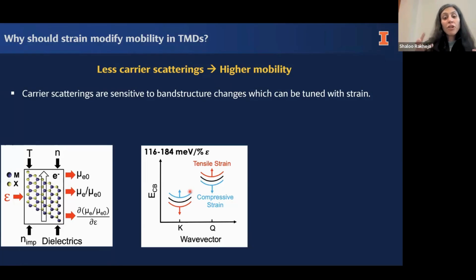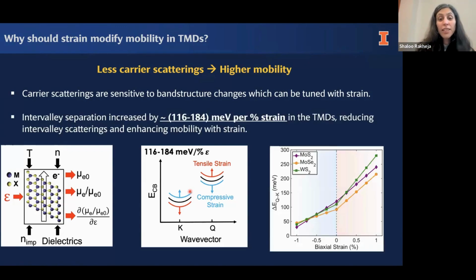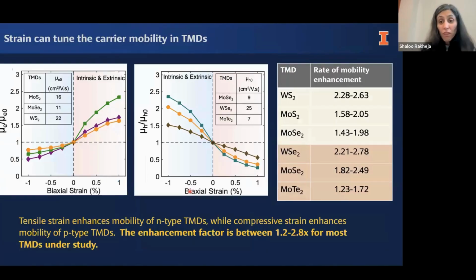On the other hand, if I have compressive strain, meaning I put the materials together, for a P-type material the same story occurs: we can prevent intervalley scatterings. And we've actually shown through atomistic calculations that intervalley separation increases due to strain for all of the TMDs, which enhances their mobility. So this is the result that I want to really emphasize.